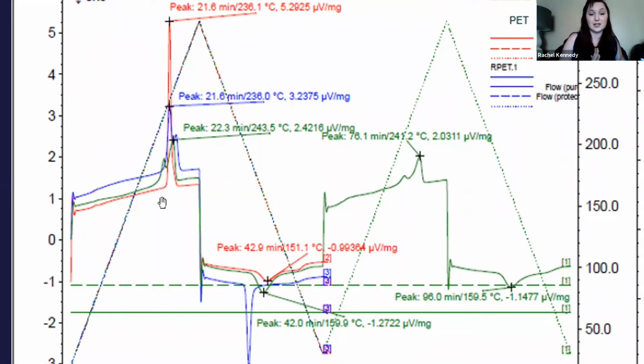The reason that there's 2 peaks is really important because this shows 2 good things. One, the fact that there's 2 defined temperatures means that your sheath and your core do melt at different temperatures. So you can isolate the melting temperature of your sheath to make sure that you get the matrix without compromising the fiber. The other good reason is that because it doesn't merge together to make one large peak, you have, again, a defined processing window, which is a little bit larger than what's available in industry at the moment with the polypropylene version, which is one of our big strengths for this project.